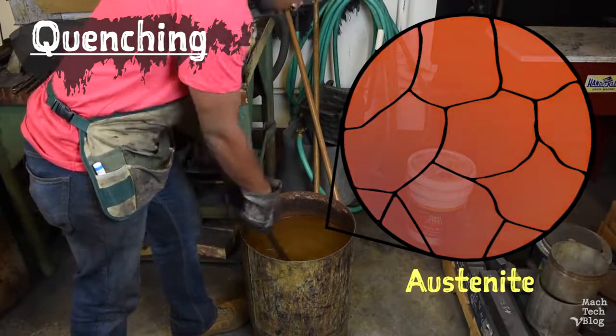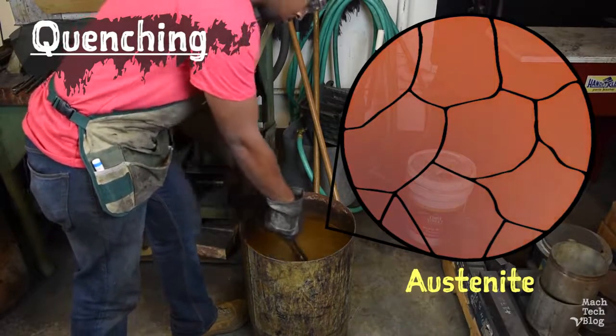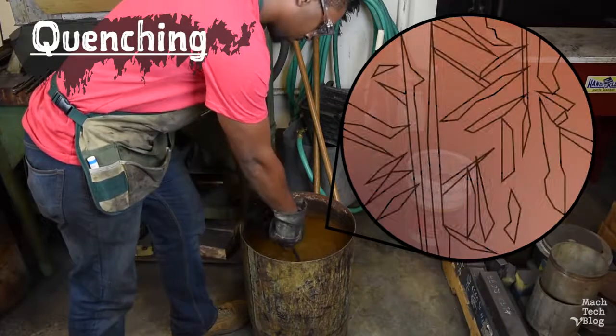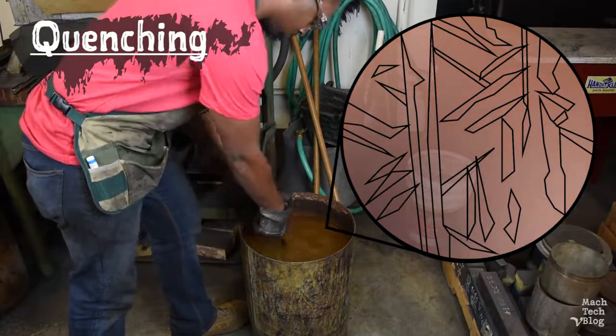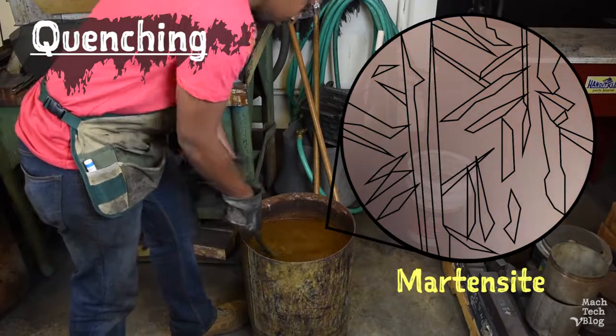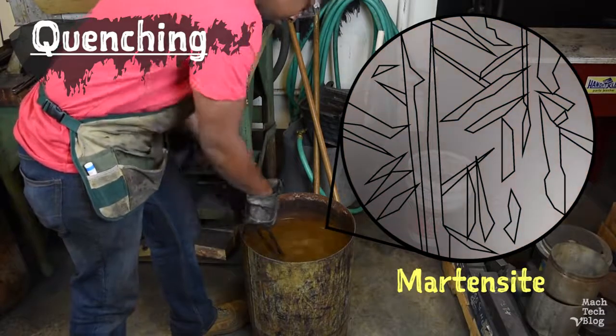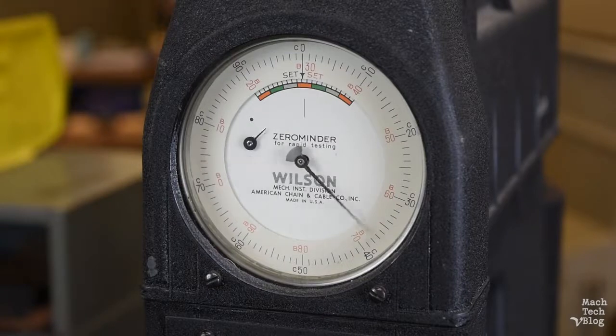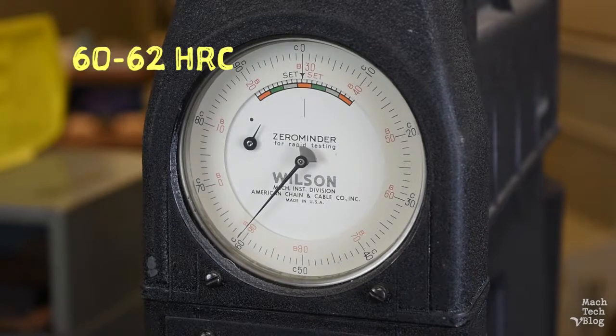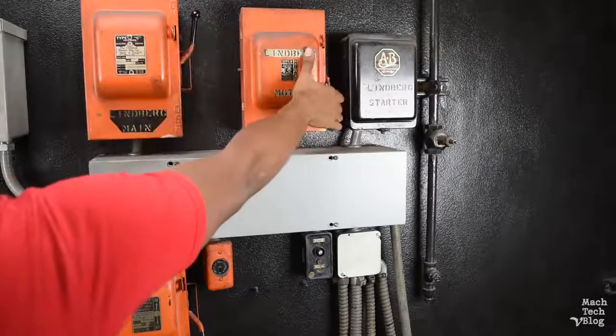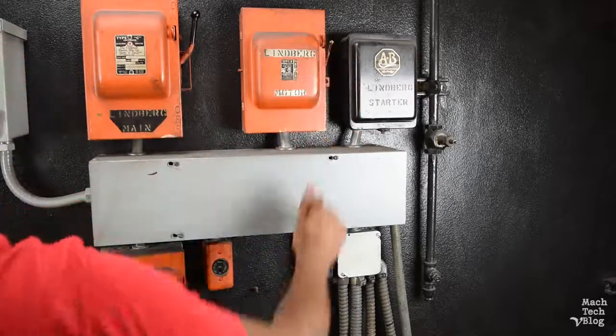Because we're cooling the steel so rapidly, the austenite won't have enough time to separate back out into iron and iron carbide. The resulting steel microstructure, called martensite, is composed of needle-like shards of iron supersaturated with carbon. Martensite is very hard stuff indeed. But the harsh process of quenching leaves a lot of internal stresses in the steel. And that's why it's common to stress relieve quenched parts by heating them back up to a relatively low temperature and holding them at that point for some amount of time.